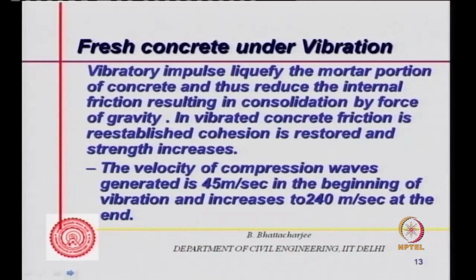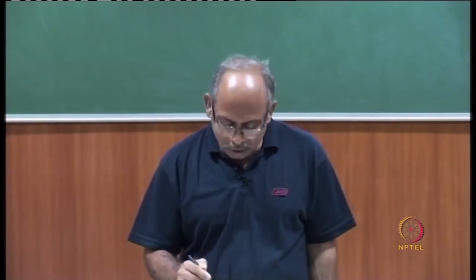So the velocity of compression waves generated could be of the order of around 45 meter per second in the beginning of vibration and increase to 240 meter per second at the end. So essentially liquefaction of the mortar occurs. That's because the water within the pore system would vibrate more or move more than the solid particles and cause an excess pressure in the system, and that overcomes the friction within the particulate system, and results in mobility or movement of the particles, and also drives out the air.